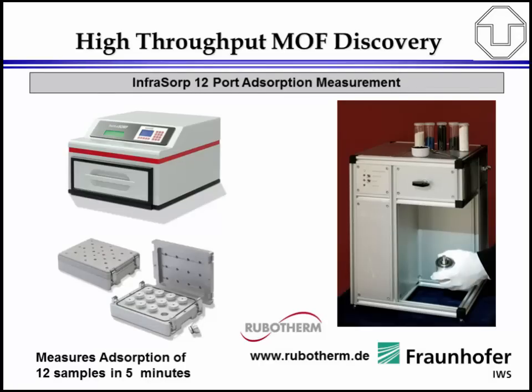Okay, on the next slide, I show that nowadays many porous materials were discovered. I just want to highlight that here people have now discovered also high-throughput methodology that allows you to extremely rapidly check if a new material, a MOF, is porous or not. This is just one example. For example, Rubotherm have developed a 12-port measurement system which allows measuring 12 samples in 5 minutes with a special technique, the so-called InfraSorp technique. But also other researchers have contributed to new high-throughput testing methods that allow nowadays to very rapidly discover new and highly porous metal organic frameworks.